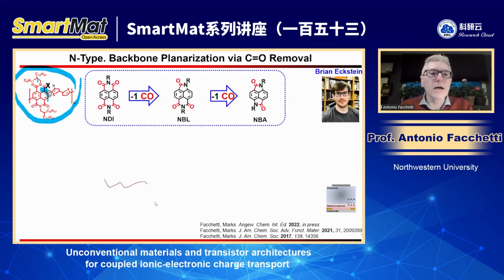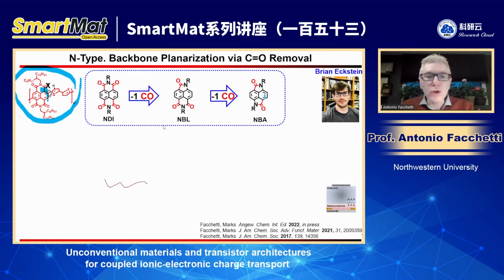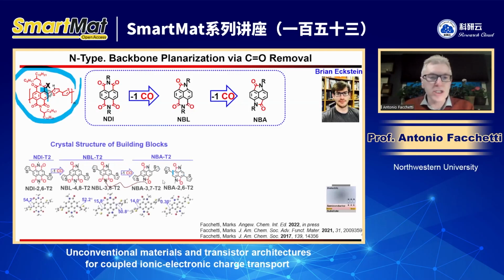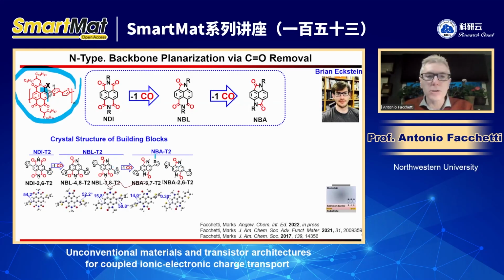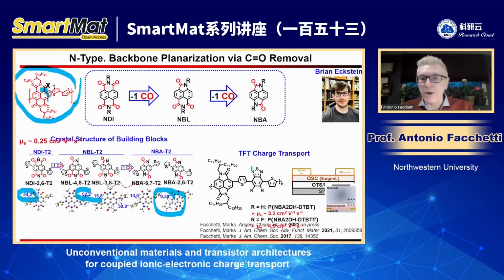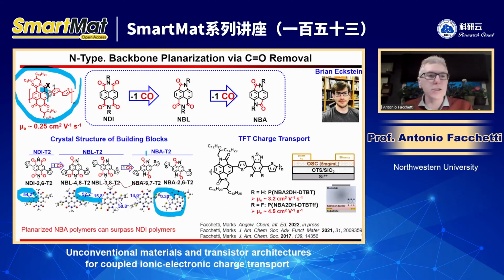So what we have done here is to remove progressively one carbonyl group from 4 to 3 to 2. If you do this, these are the molecular structures from 4 carbonyls, 3 carbonyls, 2 carbonyls. These are crystal structures. These are not computations. And you see here that the average torsional angle is decreasing, particularly for the very last unit. And when you have this type of unit combined with a proper monomer, we can actually achieve quite high electron mobility, much larger than the standard N2200. There is chemistry you can do to do that.